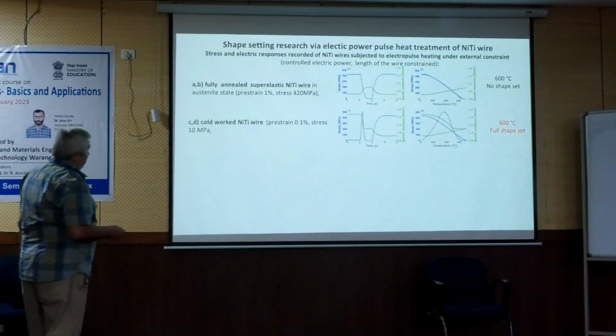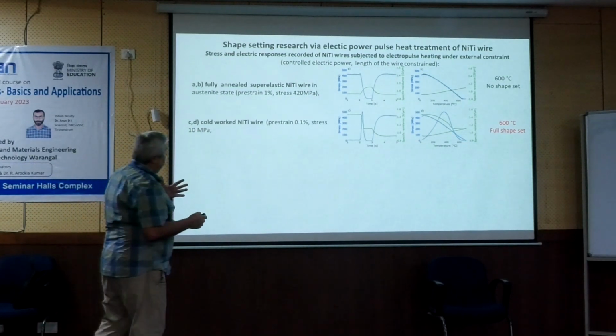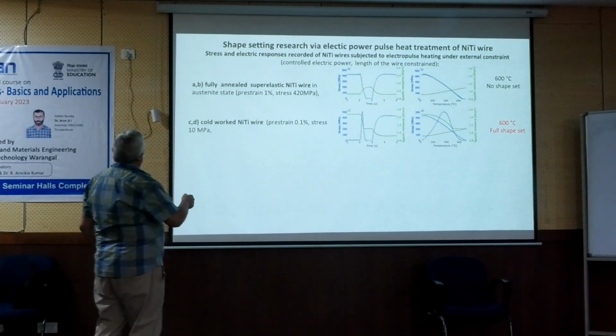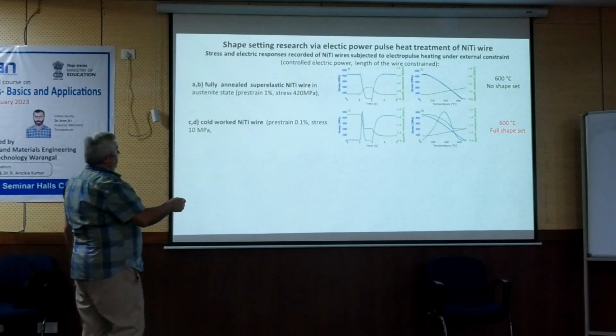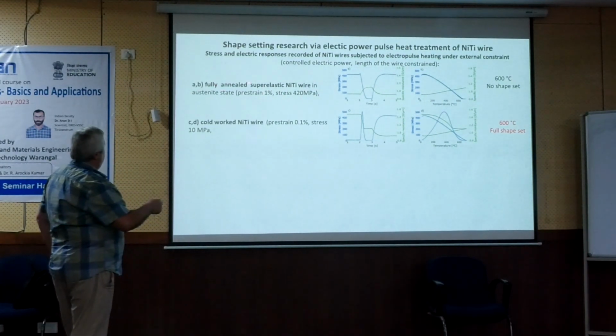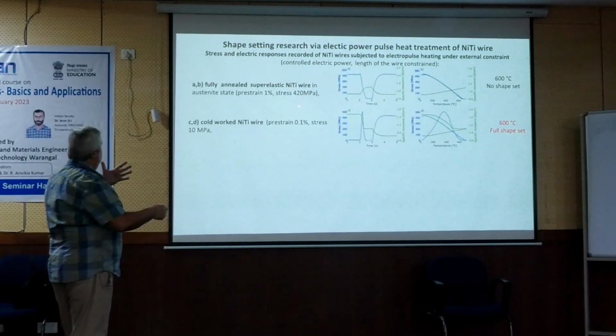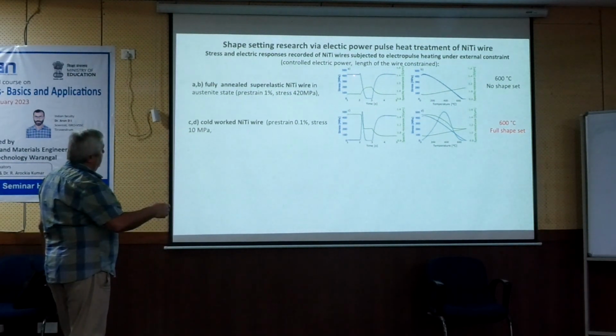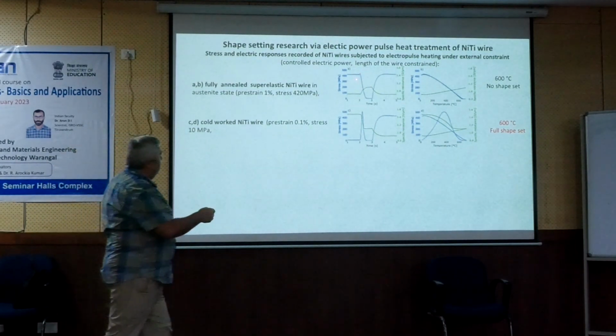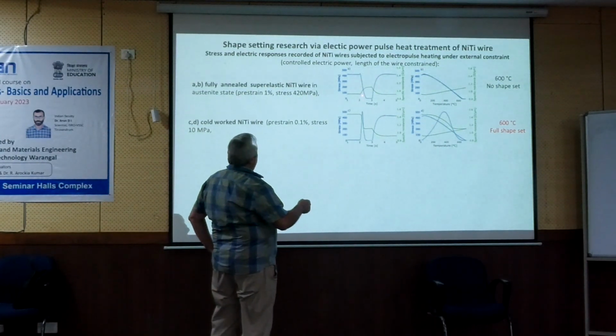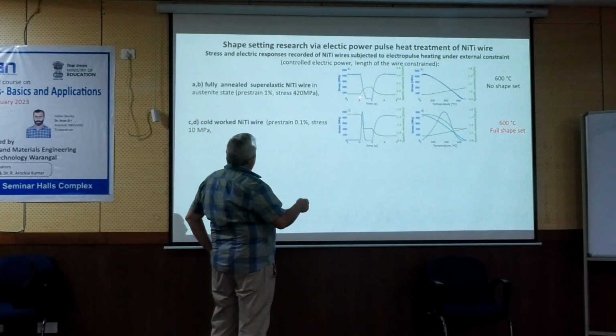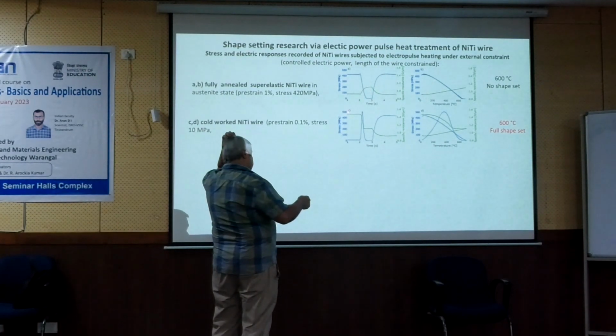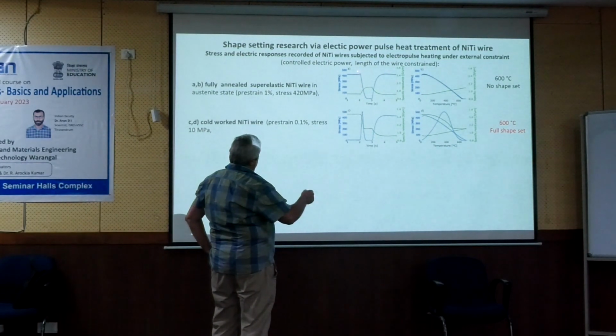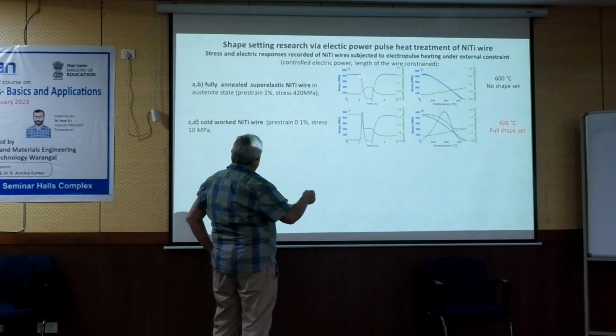And now, this is the example of some shape setting trials. So I can take a wire which is fully annealed, super elastic NiTi wire which you buy, and then you load it to 420 megapascal, and you heat it up by Joule heating. So this is here.